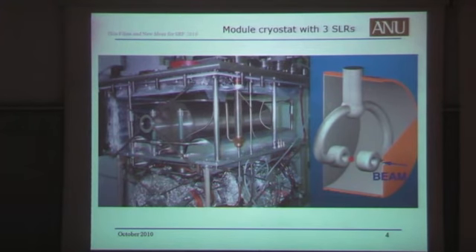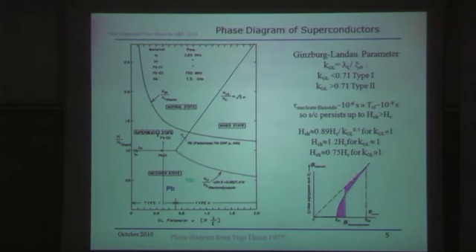So thanks to Enzo, we already have this very nice diagram from Yogi's thesis in '77, and it just points to the fact that with lead we can expect a superheated field which is about 1.2 of the critical field for this material.